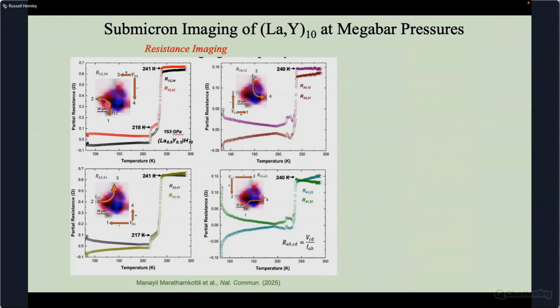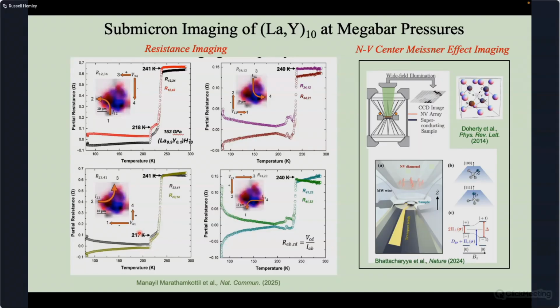So this is a kind of resistive imaging that we're combining with the X-ray imaging. And we can see that when we have material and we're measuring resistance between electrodes where we have a mixed phase, we see both steps. When we have what looks like the pure phase, the cubic phase, we have the high TC, so we can correlate the high TC phase with the cubic structure and the lower TC phase with the hexagonal structure.